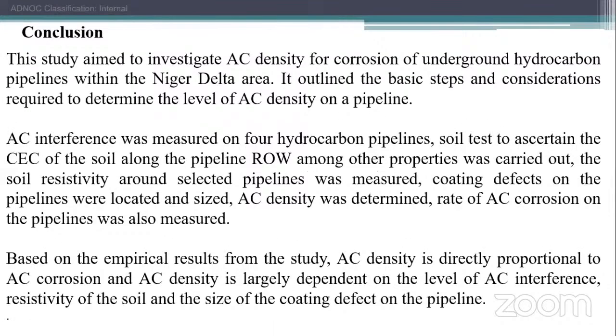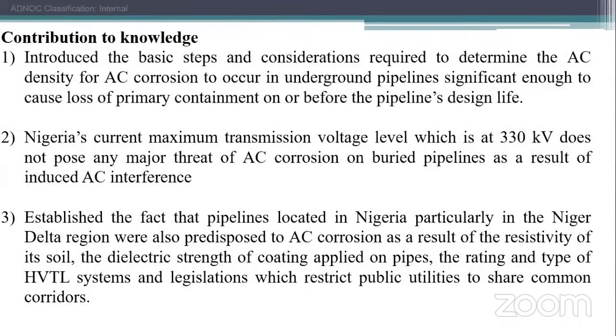But basically, the main fact is that the Nigerian current maximum transmission, which we have at 330 kV, does not pose a major threat. The AC density that we are accumulating from the 330 is not as significant currently that we should be afraid of.